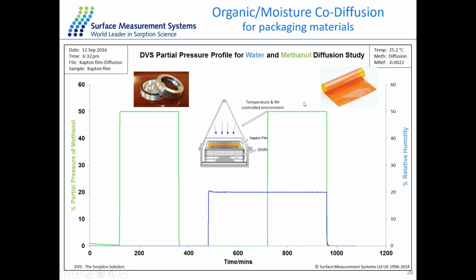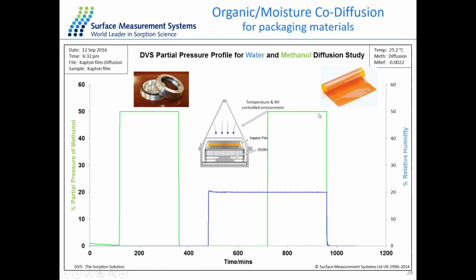And the last stage is the combination of 2 components. So we introduce 50% methanol in the presence of 20% water as the background, and we want to study the effect of the background humidity on this methanol diffusion. So we perform the experiment. Actually, I don't have the data here, but we performed the experiment at 2 different temperatures.